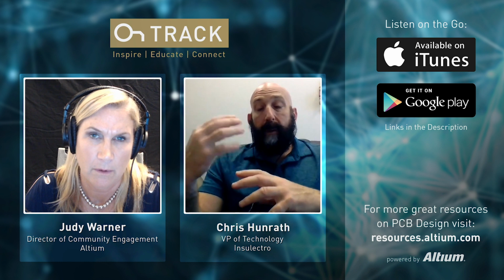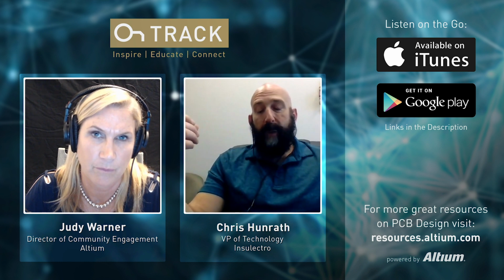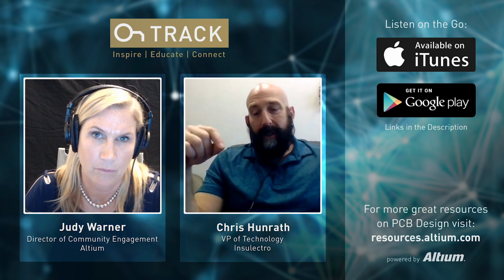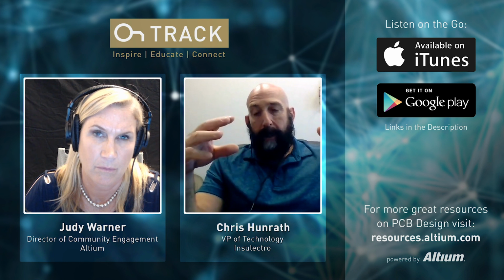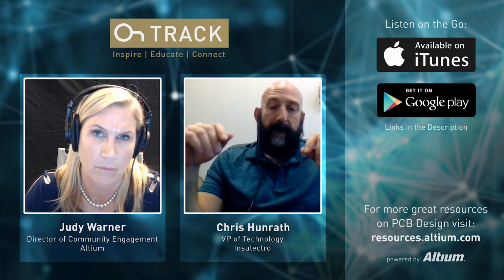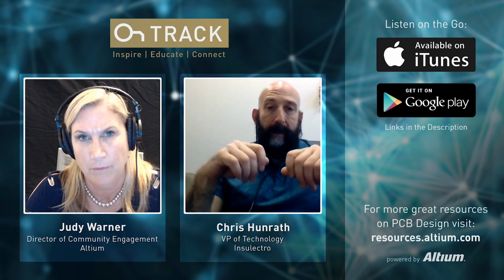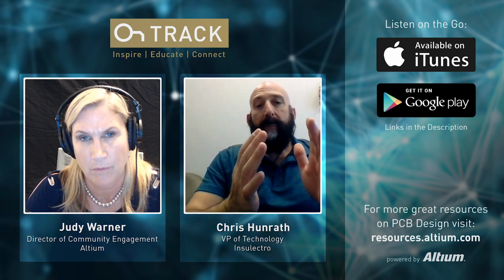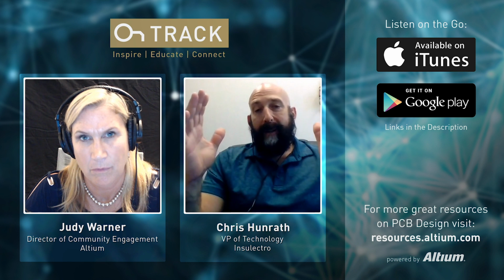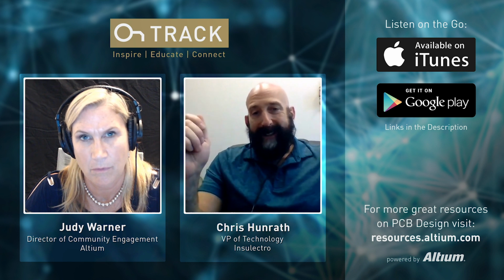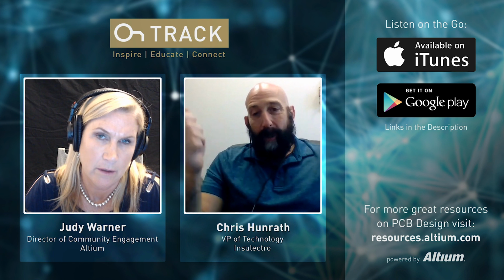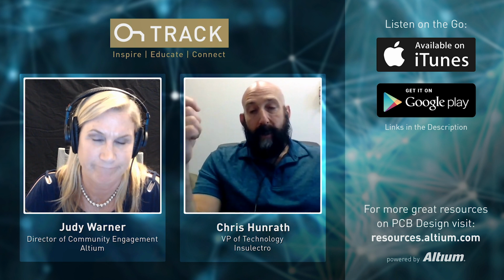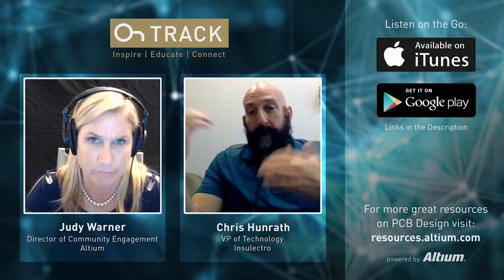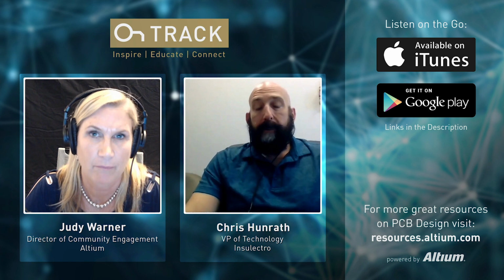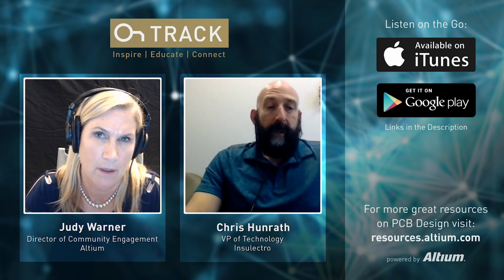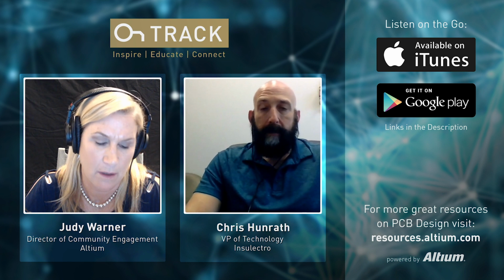Okay. So you could literally take a piece of prepreg, laser drill it with a stencil or with a Mylar stencil, and I'll talk about how that works in a little bit. Apply the paste, remove the Mylar, laminate it between two copper foils, and now you've got interconnects inside a double-sided core. That's cool. So then if you print and etch that, now you've got a core with connections between the layers with no visible vias. They're all internal. That's cool. There's some technology around the paste, and again, we could talk about that in a little bit.